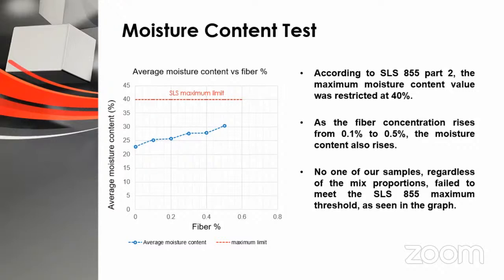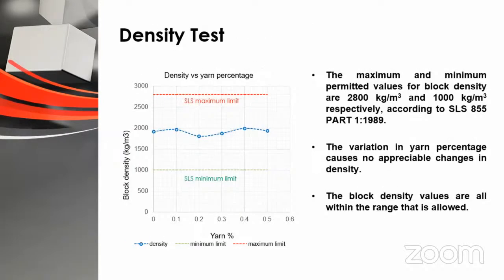Density test. The density test reveals that a denser cement block often offers more strength and fewer voids and porosities. According to SLS 855 Part 1, the maximum and minimum allowed values for block density are 2,800 kg per cubic meter and 1,000 kg per cubic meter respectively. As seen in the graph, there are no significant changes in density caused by variation in the yarn percentage. All of the block density values fall within the permissible range.